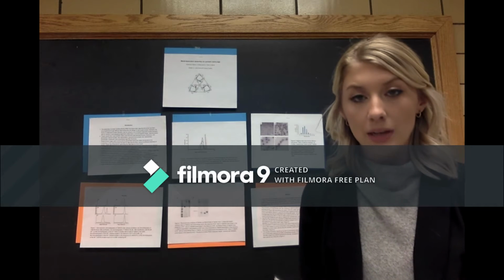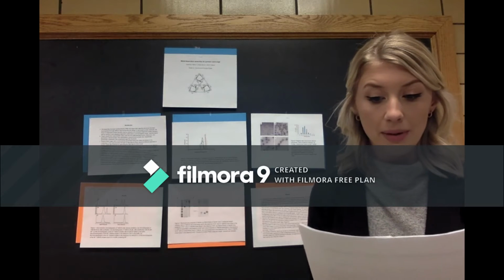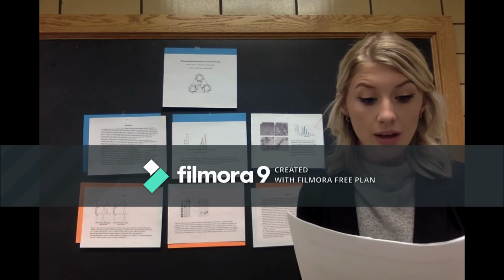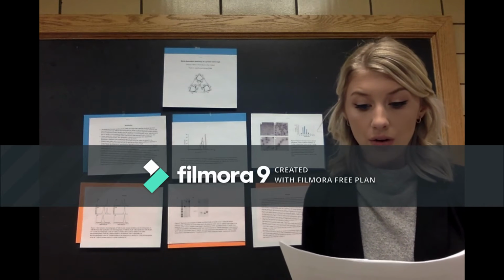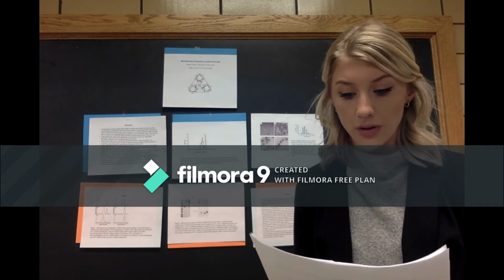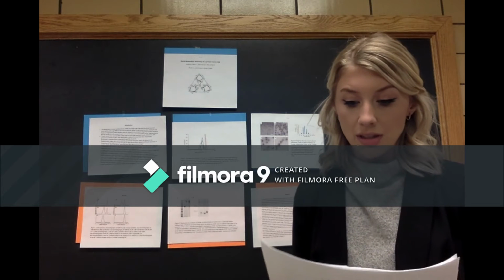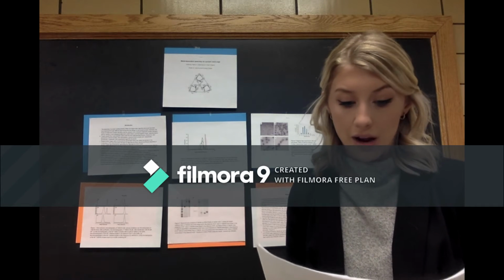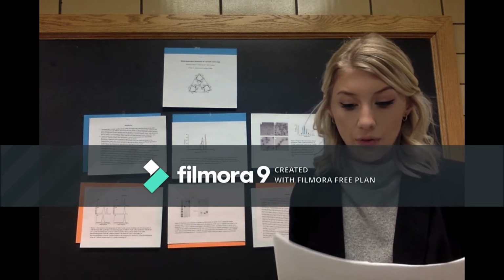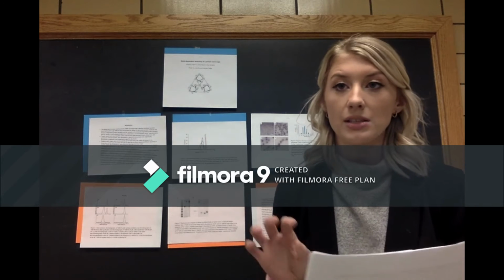To design a metal-dependent protein cage, researchers use a trimeric esterase, or tri-est, as the PBB to assemble tetrahedral, octahedral, and icosahedral protein cages. To assemble a trimeric esterase into a metal ion-dependent tetrahedral cage, a de novo designed 4-heptad coiled coil designed to oligomerize into a parallel trimeric 3-helix bundle in the presence of divalent transition metal ions was used, and a metal binding site was introduced in between to allow for 6-coordinate metal binding sites with His residues at 2 places per coil.